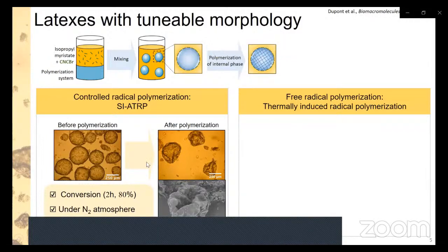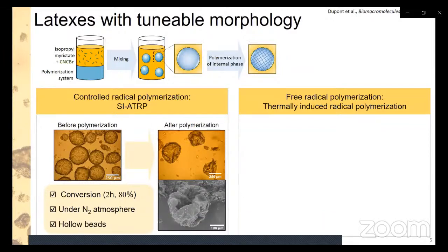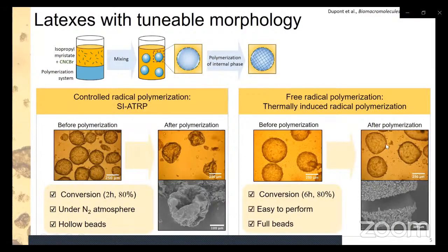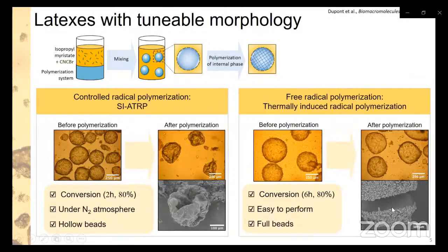So, however, this reaction must be performed under a nitrogen atmosphere, which makes it quite tricky to perform. So we preferred to work with the free radical polymerization. And this time, we obtained full beads after polymerization, as you can see here by SEM. You can see a cut inside one of the polymerized beads. It's full with polymer. So this reaction was easier to perform, and we accessed a similar conversion in only 6 hours, so it was reasonable.